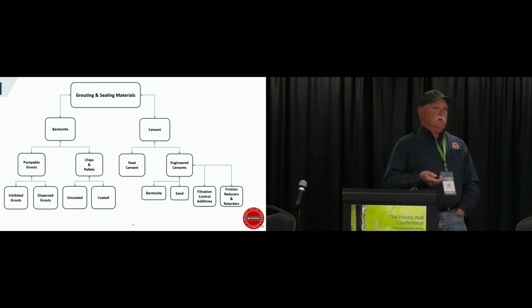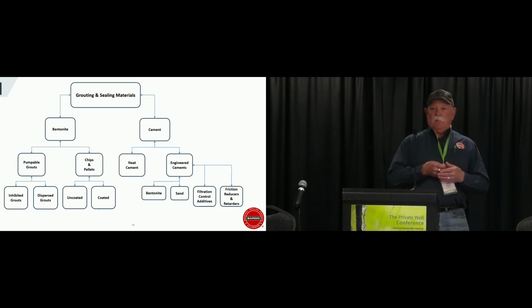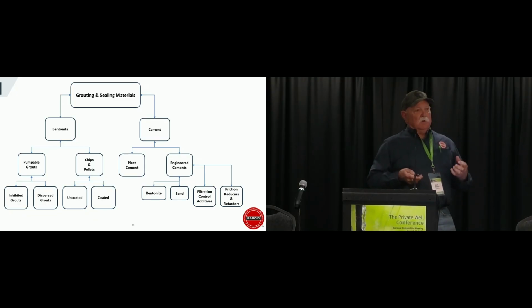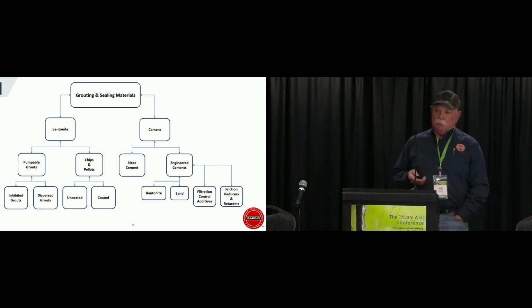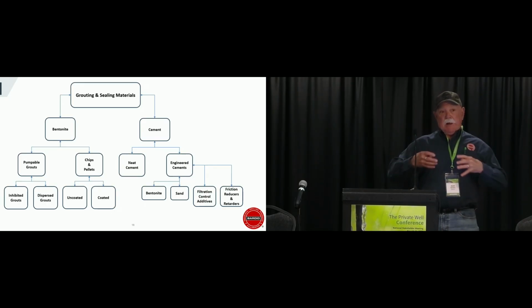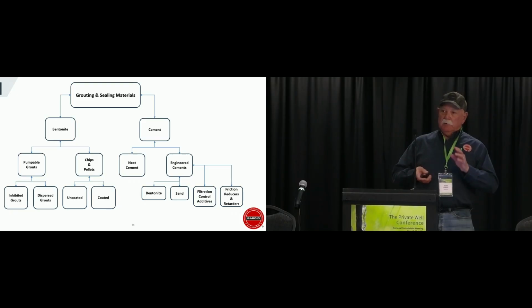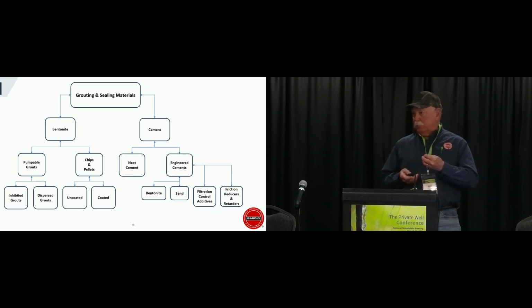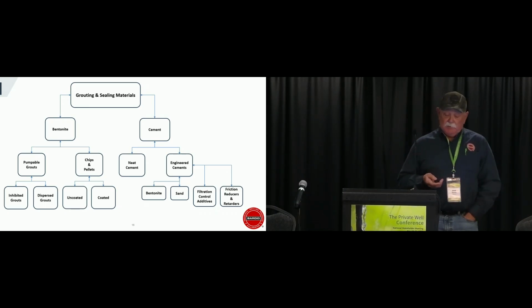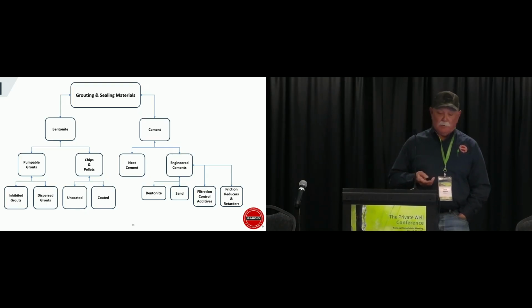Maybe some of you have seen pellets. There's a company called, I think, PDSCO. They take 30 mesh material and squeeze it together at 3,500 PSI, and the inherent moisture content in the clay will create a nice little pretty pellet. Many engineering firms require them because, well, they're kind of pretty, and they seem to pack really well. But if you consider it, it's a 30 mesh material versus a 3/8 inch solid piece of clay, so the seal isn't probably going to be as good as a chip bentonite.